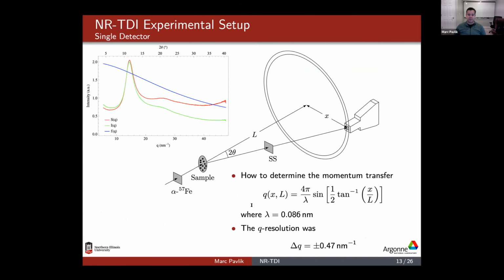Our initial setup used a single detector, which, using this geometry, allows us to position X by using our peak scattering intensity, that is, the 14 inverse nanometers. What's nice about this is we get a high Q resolution. And when I say high Q resolution, it's actually a low value. If we're measuring 14 inverse nanometers, here we're measuring anywhere from 13.5 to 14.5. Unfortunately, the count rate is very low. I think we were getting half a hertz or 1 hertz when we were doing this.